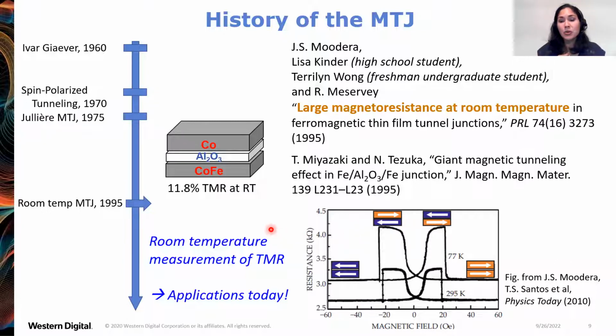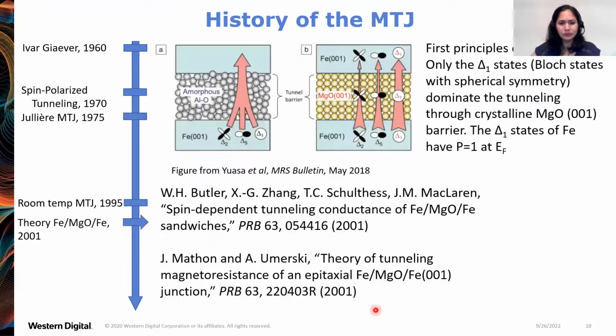But before I say a few more words about these applications, I want to cover a couple more important milestones for magnetic tunnel junctions along the way. In 2001, there was a first principles calculation saying that if you use iron electrodes and magnesium oxide tunnel barriers, you'll get a special situation that when you have an epitaxial arrangement of the atoms across the interfaces between the iron and the MgO, you'll get fully spin polarized electrons in the iron, so polarization 100%.